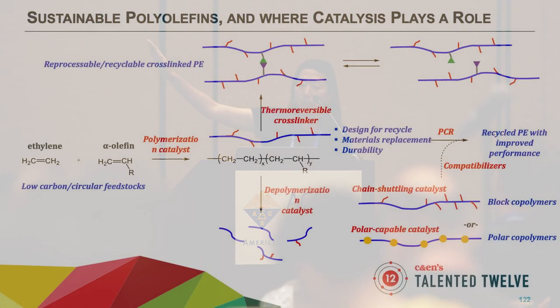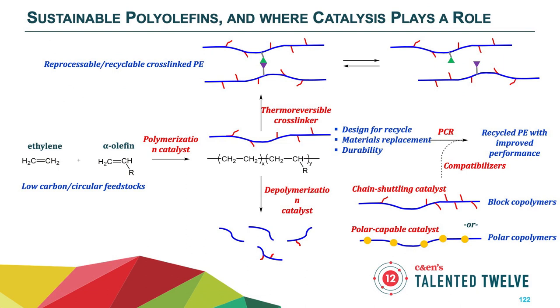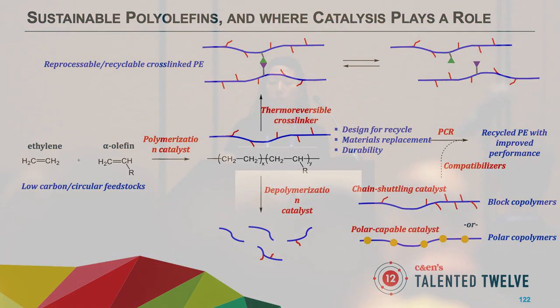Additionally, the arrow pointing to the right here reflects an increasing push to incorporate more and more recycled content in the form of PCR, or post-consumer recyclate. Oftentimes this is challenging because the quality of that PCR really varies. In order to improve the performance of PCR-containing materials, this is an area where catalysis can really play a role, where you can develop catalysts that form high-performance polyolefins that act to boost and compensate for the lack of performance you're getting from the PCR. With this blended material, the boosted resin and the PCR, the application can be a lot higher than, for example, the PCR by itself, where the applications would be limited based on the quality.